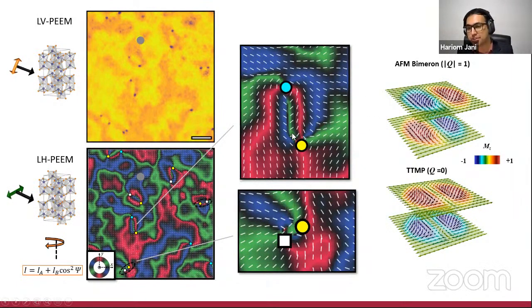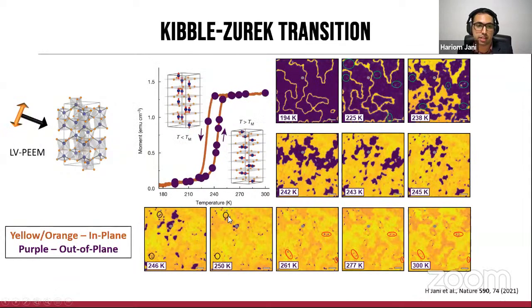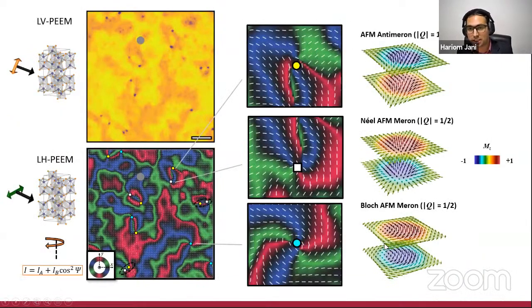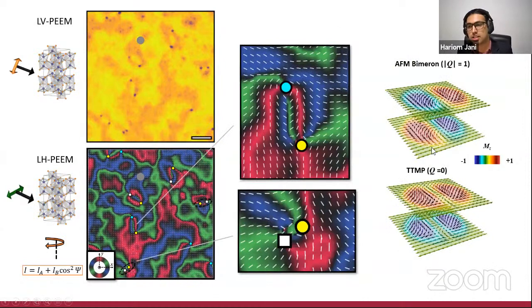Now, these pairs could be either an AFM bimeron, as I had mentioned earlier, or a topologically trivial meron pair, depending on what their core orientations are. Of course, unfortunately, we're not able to resolve the core, so we can't tell which is which. But our suspicion when we originally did this work was that the textures which annihilated could perhaps be topologically trivial pairs, as in my image here, whereas the ones that survived could be non-trivial. This was our belief at the time, and in order to really understand this and ground it, we are doing further work. But nonetheless, we do know that individually these objects are topological with charge value half.